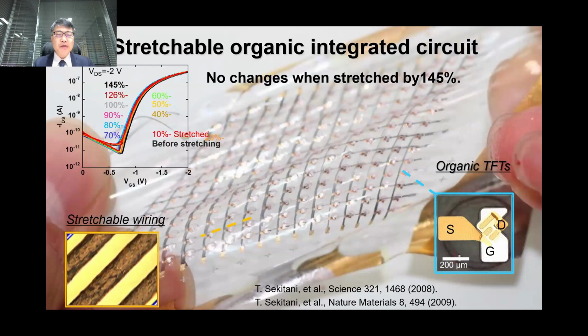So in that way, when we stretch our integrated circuit, all the strains could be accommodated by changing the length of wires. Thereby, the strain is not induced into the active layer like organic thin film transistors. So in that way, we can achieve a high stretchability over 145% without causing any mechanical failure.